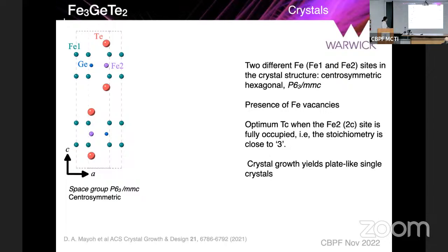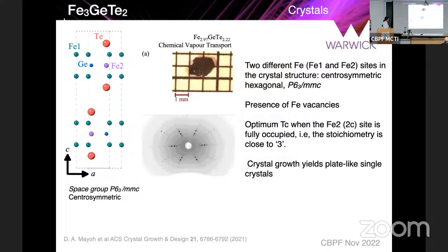In the FGT structure, there are two different types of iron sites. They are called the iron 1 and the iron 2 sites in the crystal structure, and they crystallize in the centrosymmetric hexagonal space group. Now, it so happens that in this structure, there are a lot of iron vacancies. And because there are a lot of iron vacancies, it's very difficult to achieve the optimum TC in these materials.